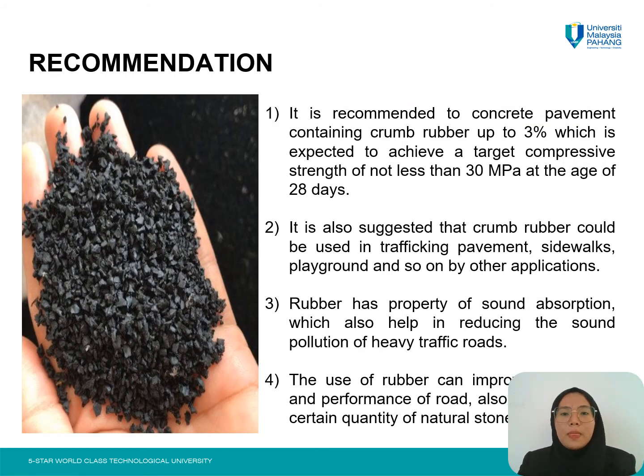For the recommendation, it is recommended that concrete pavement contain crumb rubber up to 3%, which is expected to achieve a target compressive strength of not less than 30 megapascal at the age of 28 days. It is also suggested that crumb rubber could be used in traffic pavement, sidewalks, playgrounds, and other applications. Rubber has the property of sound absorption, which also helps in reducing the sound pollution of heavy traffic roads. The use of rubber can improve the quality and performance of roads. It can also save a certain quantity of natural stone aggregate.